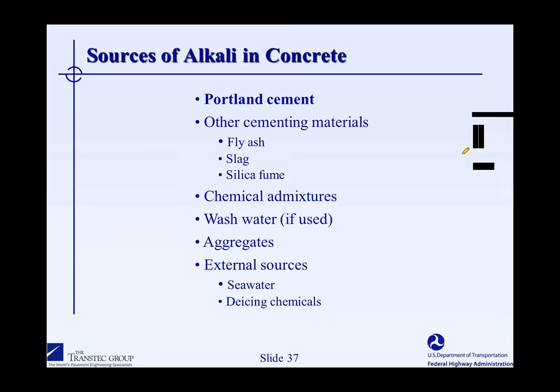And if we're trying to do an inventory of the alkalis in concrete, we really should consider including the alkalis that might be in the wash water. Aggregates themselves can contain alkalis, and this can be quite a significant contribution with some types of aggregate. However, we don't really have a standard test method for measuring the alkalis contributed by aggregates, so we tend to disregard it mostly, and that's perhaps something we need to look at more carefully in the future.